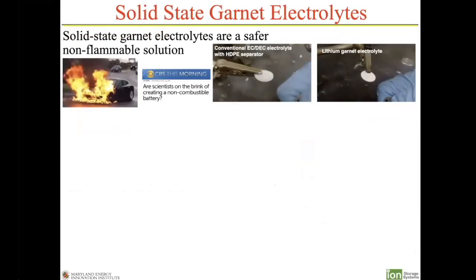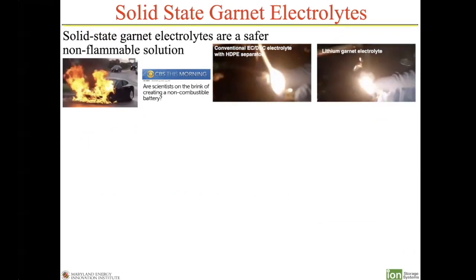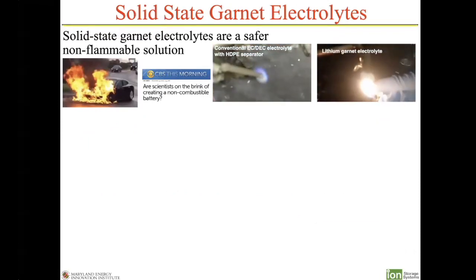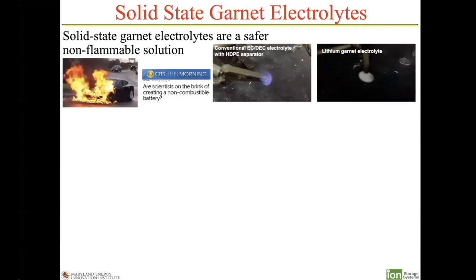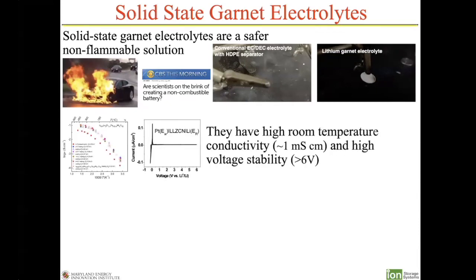Now, our approach to developing solid-state batteries is using a garnet electrolyte. And you can see the video in the middle. This is your conventional liquid electrolyte. This was done, I was interviewed by CBS News after some certain battery fires. And you can see how the liquid electrolyte just burns up. It's a flammable liquid. But the garnet doesn't do anything. We sinter this in a furnace at over 1,000 degrees centigrade. You see some carbon deposits, but it's a completely non-flammable electrolyte. So that takes away that safety concern.